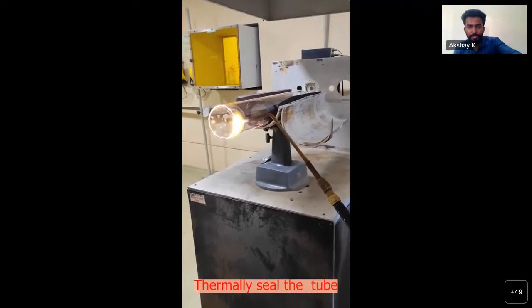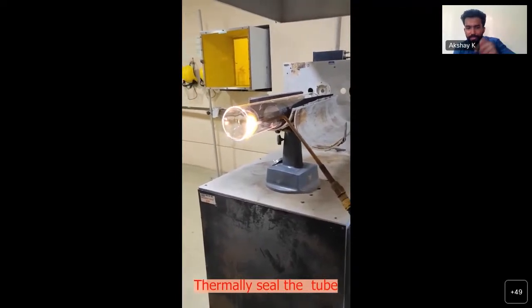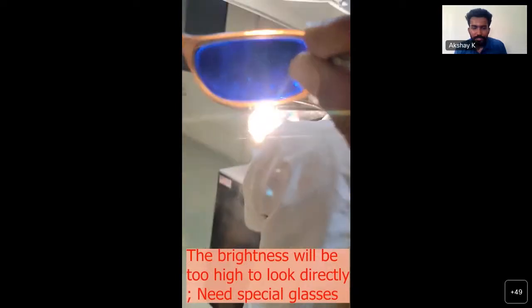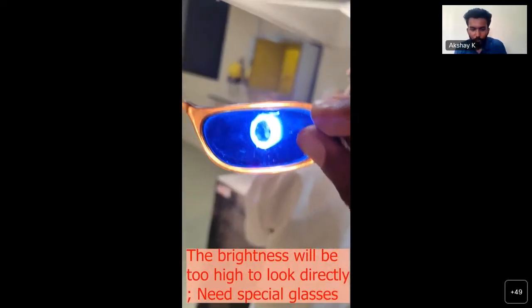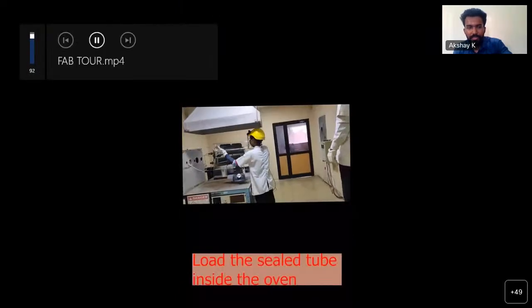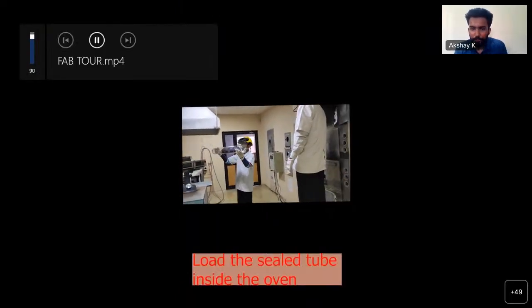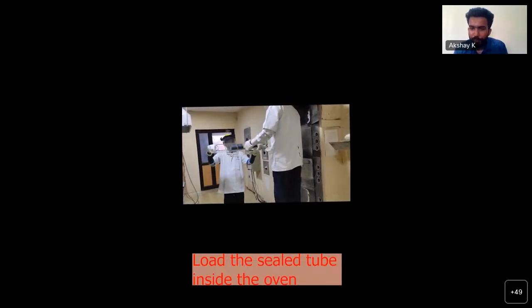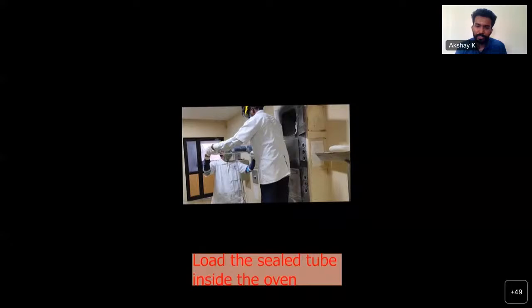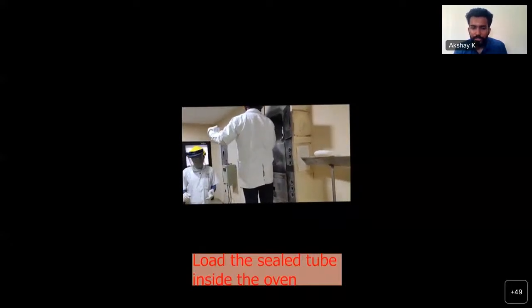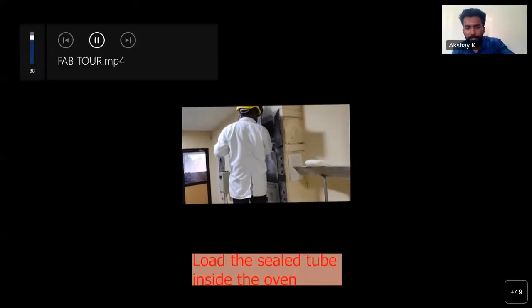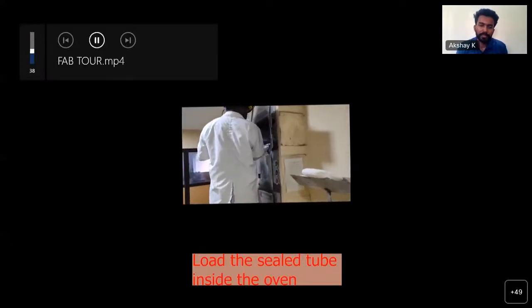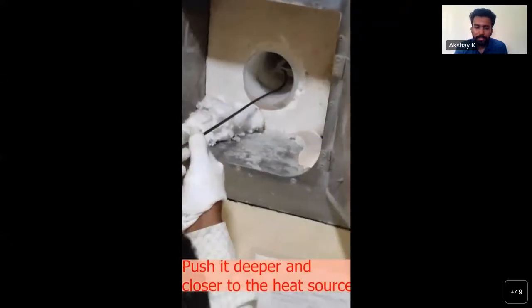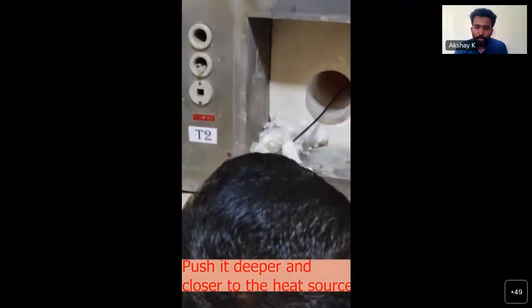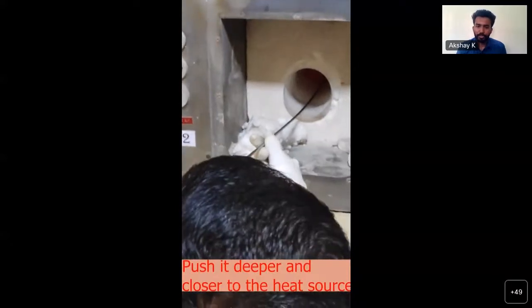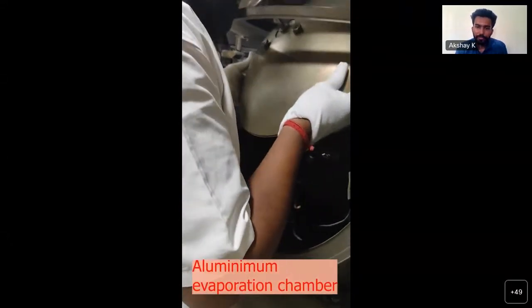There are two glass surfaces you can see, which they are going to seal by kind of welding. And it becomes so hot and bright that you would need special glasses to see through. And once you vacuum seal it, you have to take it very carefully because it's vacuum inside and it can burst out if there is any disturbance. So you have to very carefully keep it inside the oven for diffusion, which happens at somewhere around 1000-degree temperature. You push it deeper and close to the heat source, so that it uniformly undergoes diffusion.